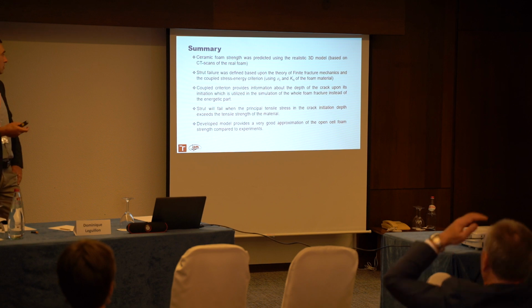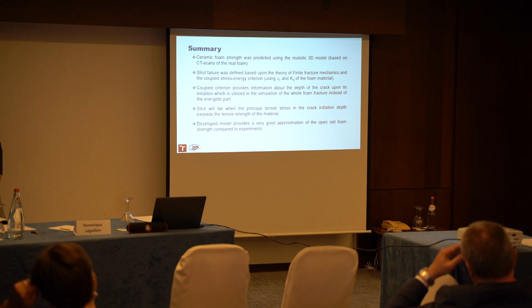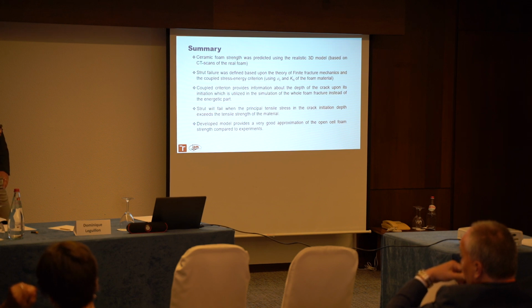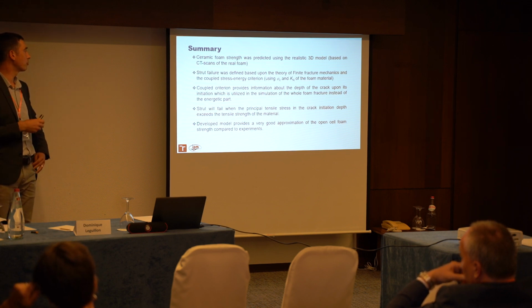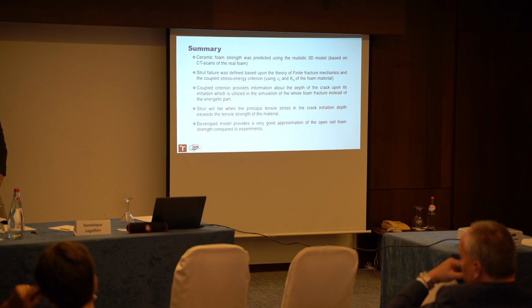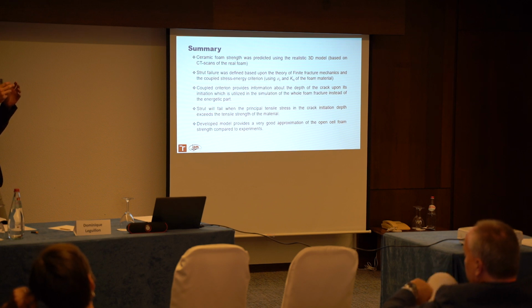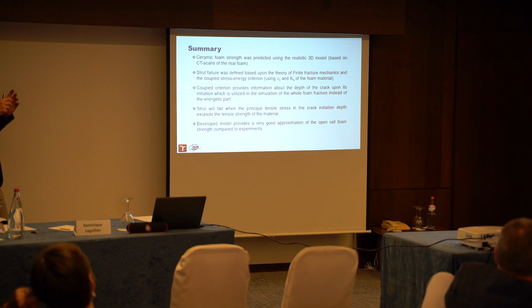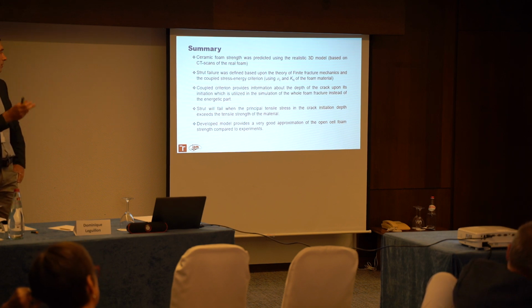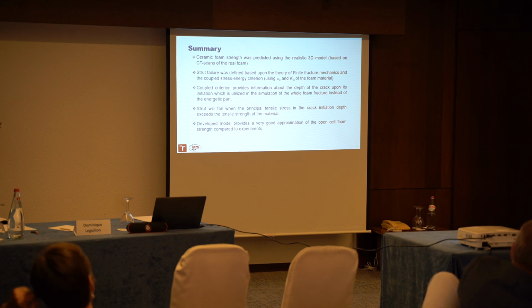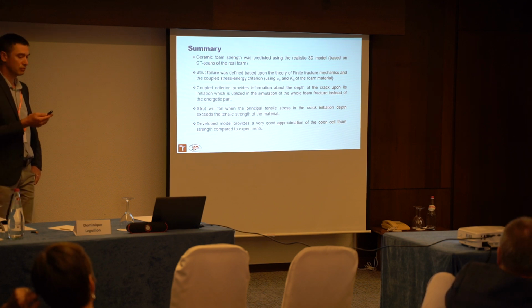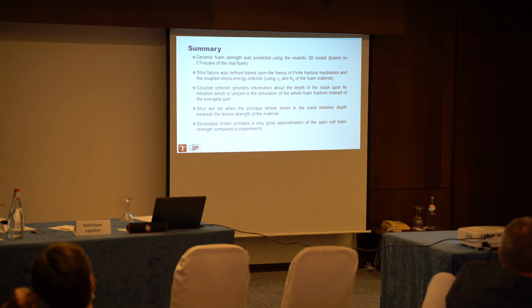Okay, so we summarize the work. We predict the strength of the foam using the coupled criterion. The important thing is that we didn't use the coupled criterion for definition of breakage of whole struts, but just for calculation of the crack initiation depth, which we then applied in the simulation of the whole foam failure. And the agreement with the experiment is very good, so it was the main result.